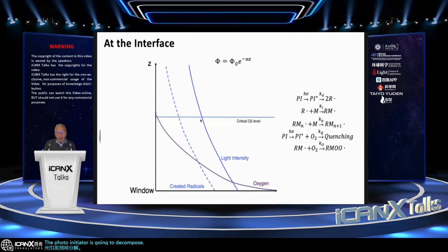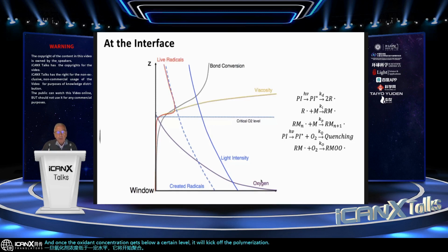Once you have a radical, it's got one of two fates. If there's oxygen present, it will be quenched by the oxygen. And once the oxygen concentration gets below a certain level, it will kick off the polymerization. And so the oxygen is being consumed by the light generating the radical pair, but it's being replenished at the interface with the window. And so there's a gradient in oxygen concentration, which basically defines that dead zone, this distance here.